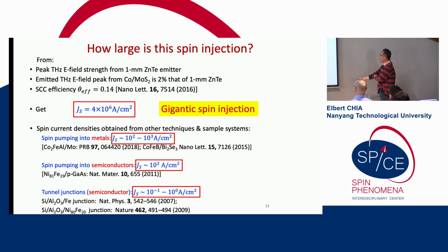We then went on to calculate the magnitude of this injected spin current density. So from the Terahertz electric field strength at the detector, we work backwards. From the detector and then at the sample position, then we calculated the charge current density, and then we calculated the spin current density, and we got this conservative value of roughly 10^6 amperes per centimeter squared. And this is a few orders of magnitude larger than that obtained from other methods such as pumping or tunnel junctions into metals or semiconductors.